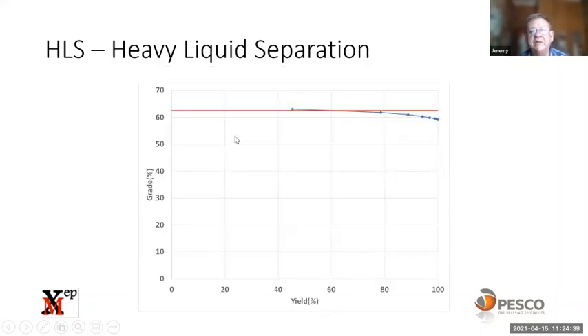If we go and look at the grade yield curve, if we're targeting a 62.5 grade, you can see we've got a yield of around about 60%. And this is one way of representing heavy liquid separation results.